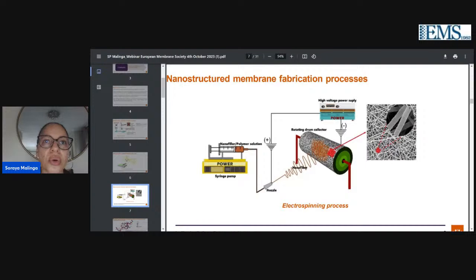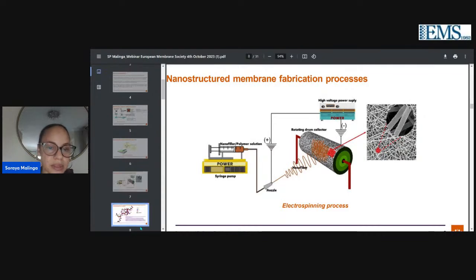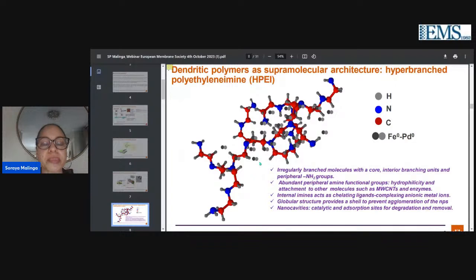This process requires, though, a lot of optimization, such as your collector distance and your polymer percentage, so that you can get ultra fine nanofiber membranes. The main focus of my presentation today is that we embarked on using this quite big molecule, hyperbranched polyethylene imine, because, as I had mentioned, it has NH2 groups on its periphery, which are quite abundant. And these NH2 groups really assist in improving the hydrophilicity of the membranes.